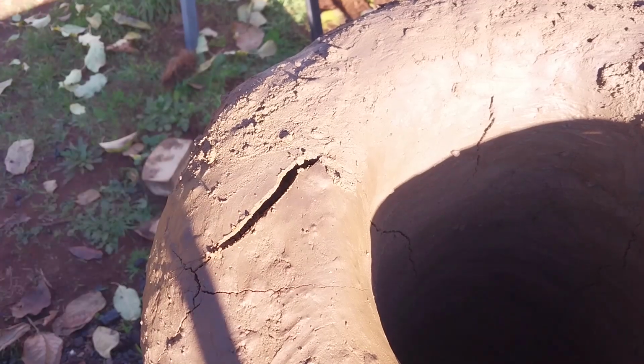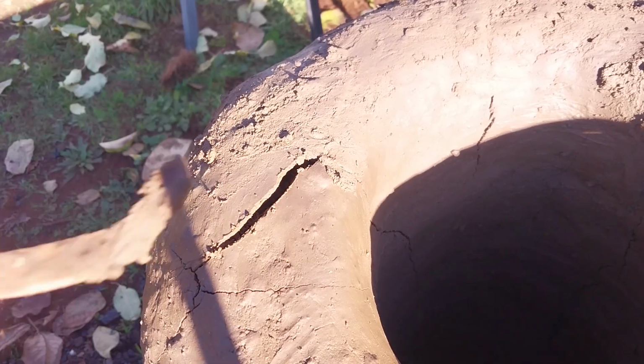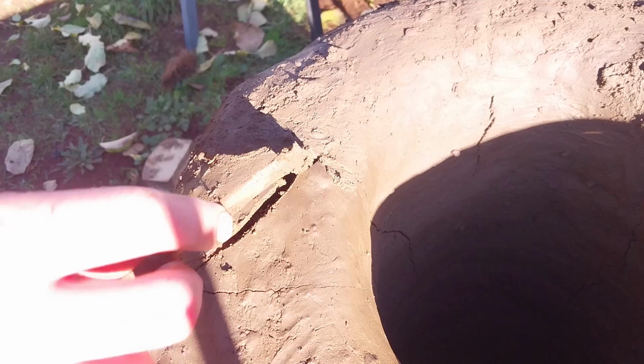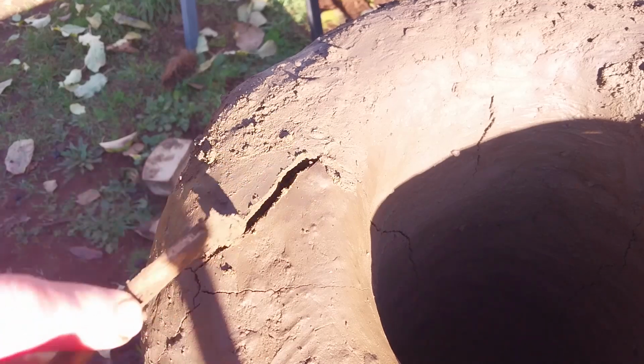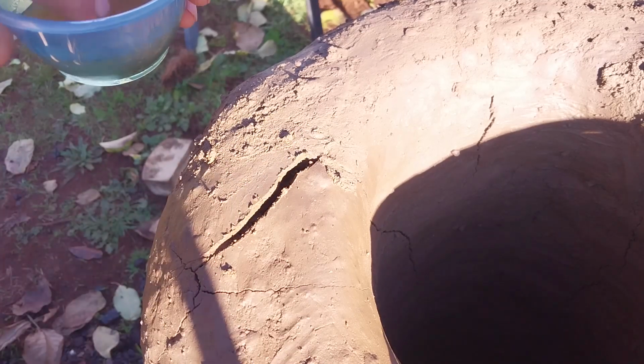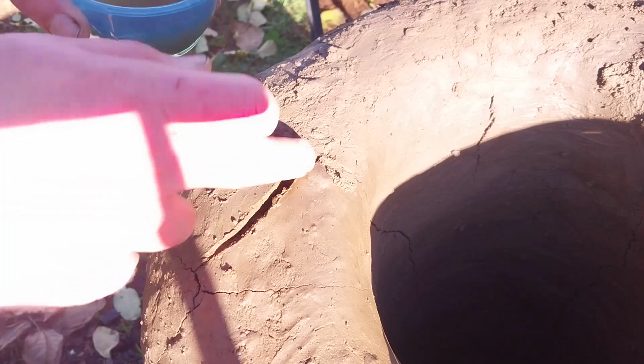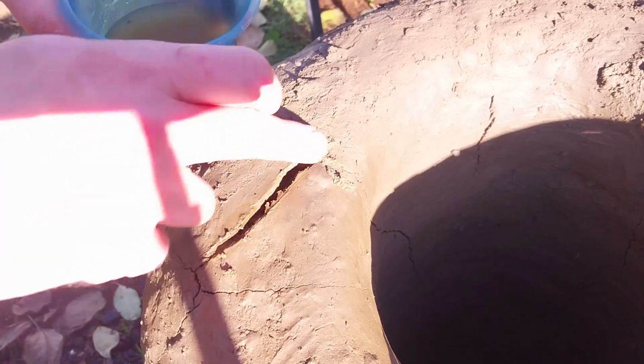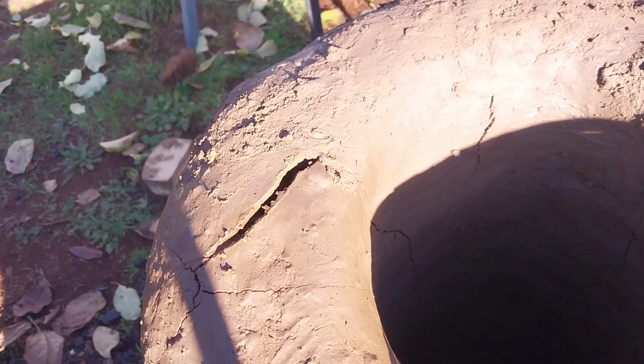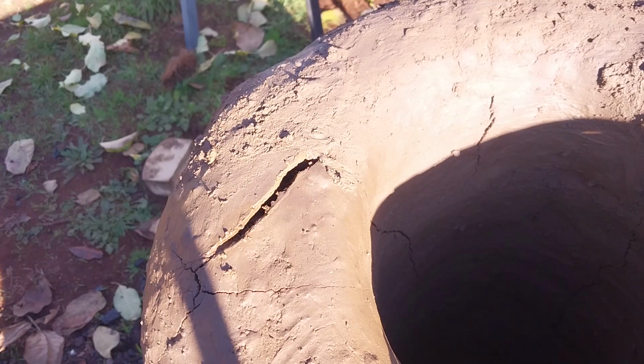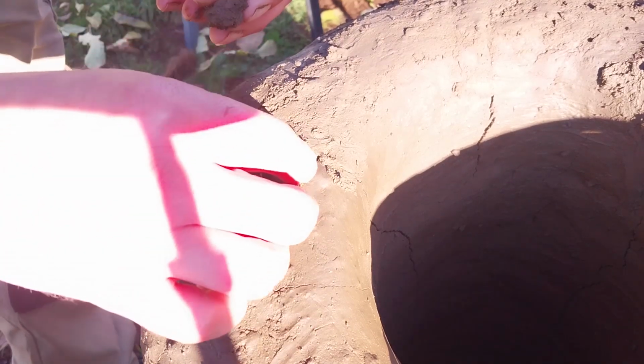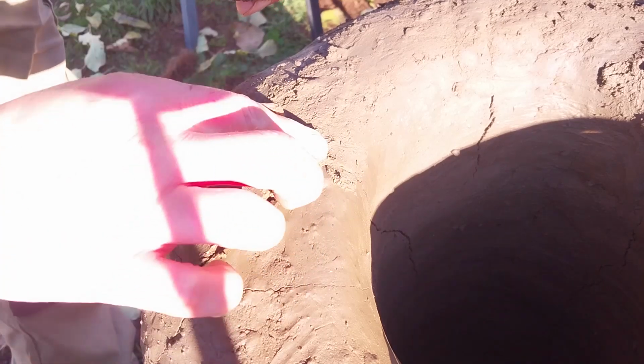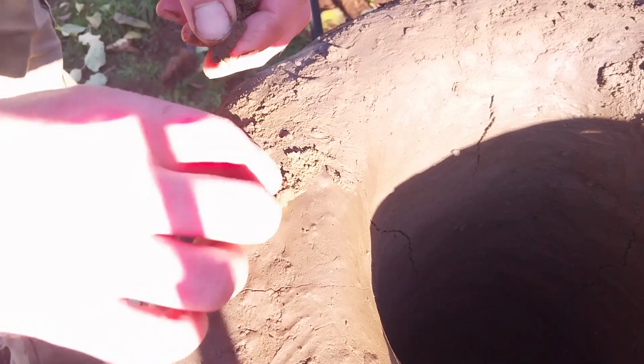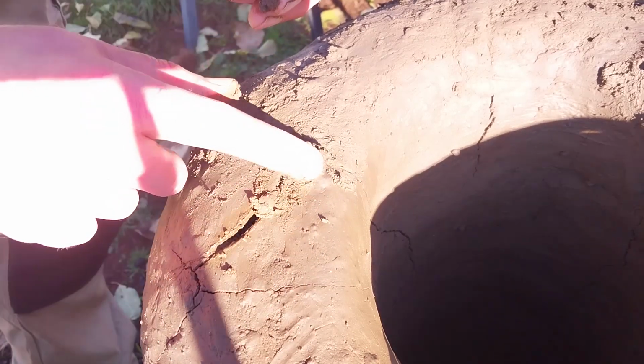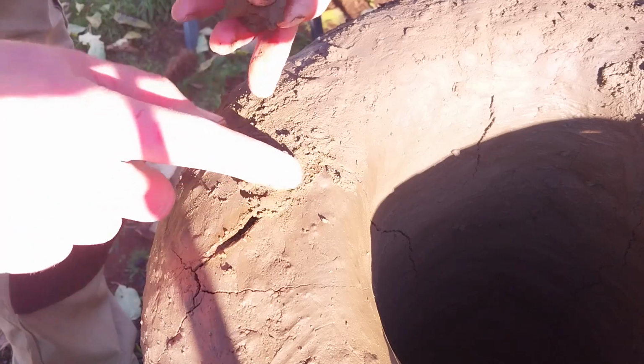So here you can see we've used our tool and we've scraped out the inside of that crack. We just want to put a little bit of moisture in there just to activate the clay. And then you want to take our mix, and the first thing we want to do is to try and pack it down in there. You'll find if you do half the crack first, it will work a bit better.